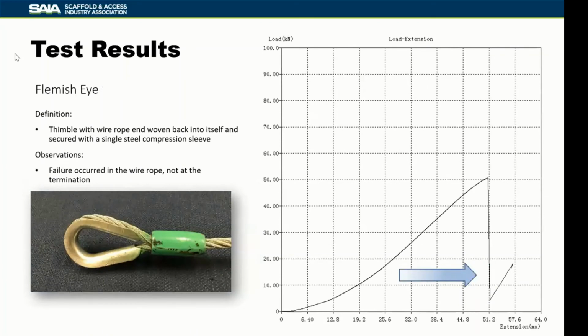Looking at the Flemish eye, for those of you who may not be familiar, there may be different definitions for a Flemish eye depending on the individual, but this is the Flemish eye as our supplier provides them. They weave the wire rope back into itself after going around the thimble, and then put a steel compression sleeve over top of that. So you get the interweaving of the strands as well as the steel compression sleeve. We get a little more elongation than on some of the other terminations, but the force is very similar, and the failure once again occurred in the wire rope and not in the termination itself.